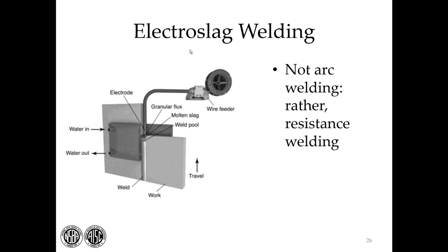One other process that is used in bridge welding, although not very commonly, is electroslag welding. With electroslag welding, the weld is built in the vertical direction. These two are the base plates we're joining in this particular weld. You'll see that there's a copper shoe that's on the outside. It's cut away here, but it would cover the weld on both sides. The shoe has got water to keep it cool. So you basically build a cavity with your shoes and your plates, and then you feed in your electrode inside a guide tube that guides the electrode, and also some flux that sits on the top of the weld puddle.